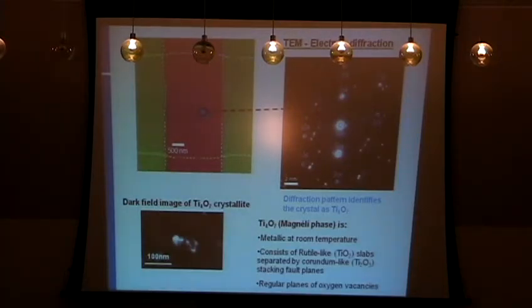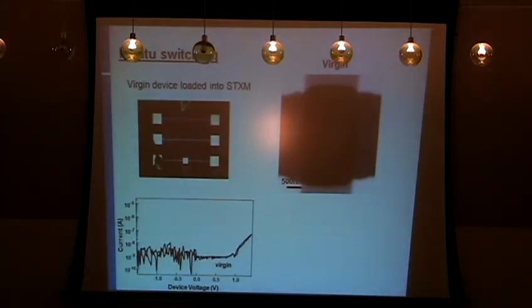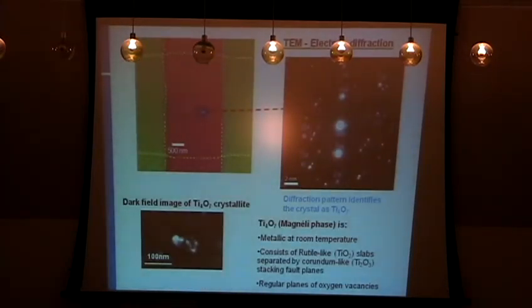A little bit about Ti4O7. This is a stable sub-oxide of TiO2. It's part of the family of phases called the Magnéli phases. Interesting for us, it's metallic at room temperature. A little bit about the structure: you basically think of it as rutile TiO2 with planes of oxygen vacancies. More precisely, you've got shear fault planes that are corundum-like Ti2O3. And so essentially, like I said, planes of oxygen vacancies regularly arranged.